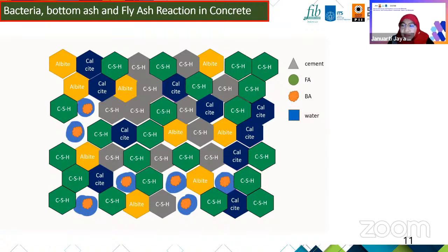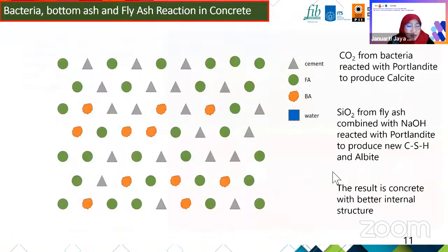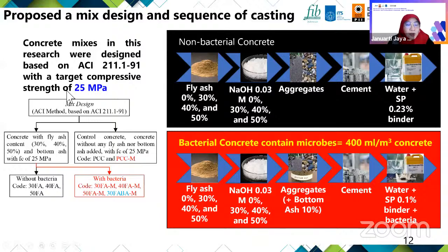In the next slide, in our experiment, we used a mix design to obtain the strength of 25 megapascal in 28 days. As a cement replacement, class F fly ash was used, at 30%, 40% and 50% by cement weight.